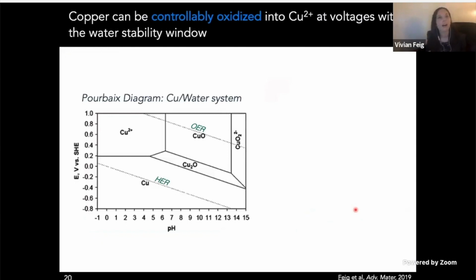For the sacrificial metal, we decided to use copper because it's easy to electroplate or evaporate onto a variety of different surfaces. And if you look at the Pourbaix diagram of a copper water system, you can also see that there's a pretty large window of voltages where this cationic form of copper is the equilibrium species. Moreover, that's happening within the water stability window, which means that you can oxidize the copper without worrying about the side reactions that might generate gaseous byproducts, which we've actually seen can physically damage the gels that are formed.